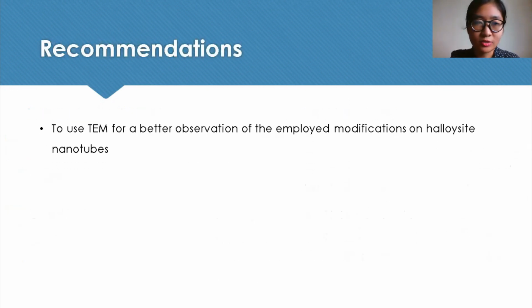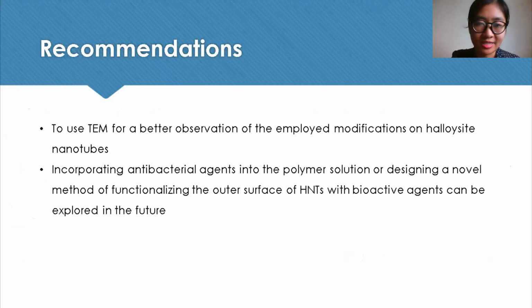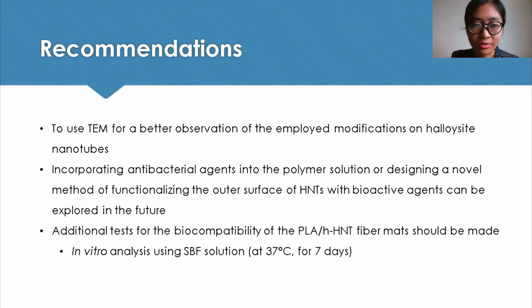Recommendations to further improve this study are as follows. It is recommended to use TEM, or transmission electron microscope, for better observation of the employed modifications on halloysite nanotubes. Incorporating antibacterial agents into the polymer solution, or designing a novel method of functionalizing the outer surface of HNTs with bioactive agents, can be explored in the future. It is also recommended that additional tests for the biocompatibility of the PLA HHNT fiber mat should be made, the simplest being in vitro analysis using SBF solution at 37 degrees Celsius for 7 days.